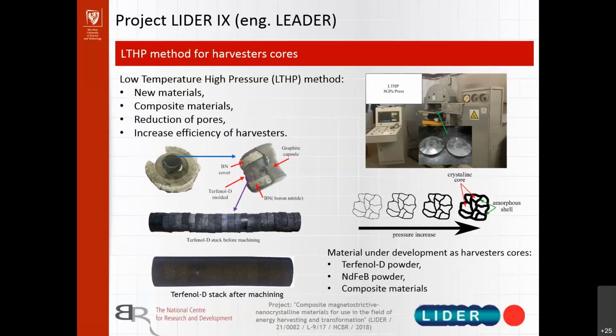We tried machining, and it turns out that the LTHP method allows us to obtain material which is hard enough, or good enough, to even machine it. It didn't break during the machining, and we obtained a pretty nice rod. You can see here the places where each tablet is attached to the others.